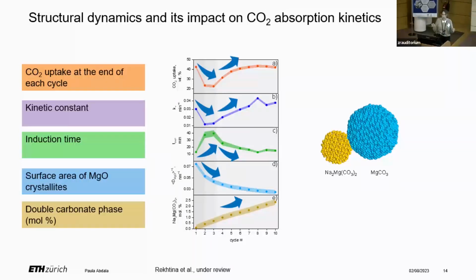When we look closely at the diffraction pattern, we observe a second phase that is being formed as we cycle. This is a double carbonate phase, sodium magnesium carbonate, that is formed from the melt and in reaction with the magnesium oxide, and it increases over the cycles. So with this, we hypothesize that this double salt acts as an effective new nucleation seed for the formation of carbonate.